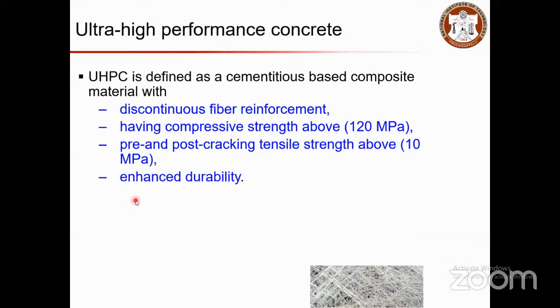Ultra high performance concrete is based on a cementitious composite material with certain discontinuous fiber reinforcement placed in it. The strength is typically in the range of above 120 MPa. Nowadays ultra high performance concretes are being used enormously for constructing high-rise buildings, so that the size of the buildings can be reduced significantly when you move to UHPC, which helps to reduce the overall dead load of the structures. The pre and post cracking tensile strength would be above 10 MPa, and